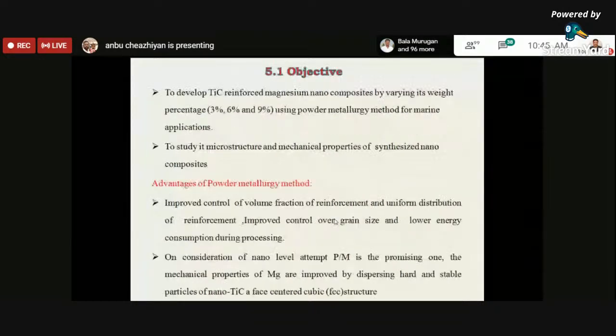So this is the objective: to develop titanium carbide reinforced magnesium nanocomposites by varying the weight percentage to 3, 6, and 9% using the powder metallurgy method for marine application, and to study the microstructure and mechanical properties of the synthesized nanocomposites. The reasons for using powder metallurgy are improved control of the volume fraction of reinforcement, uniform distribution of reinforcement, improved control over the grain size, and lower energy consumption during processing.